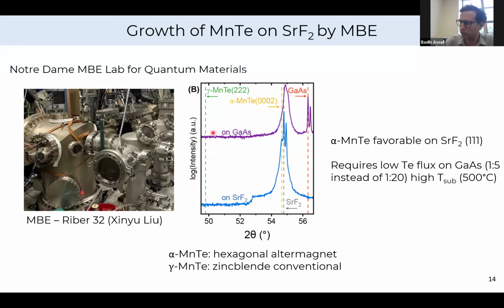What I'm showing here is X-ray diffraction patterns taken on films grown on both substrates, just to prove to you that we can control this aspect and that our films actually only exhibit this peak right here, this Bragg peak right there for gallium arsenide and right here for strontium fluoride, that corresponds closely to the alpha MnTe peak. And we don't have any signal at all on a log scale for the gamma MnTe phase.